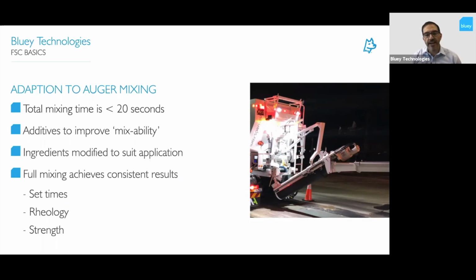So we've had to put additives in the product and change the way it was designed so that we can improve, let's call it, mixability of the product. So we've changed the ingredients to suit that application. And full mixing means that you achieve more consistent results. So you're getting more consistent set times, more consistent rheology, and more consistent strength gain. And mixing is a really important part of that.